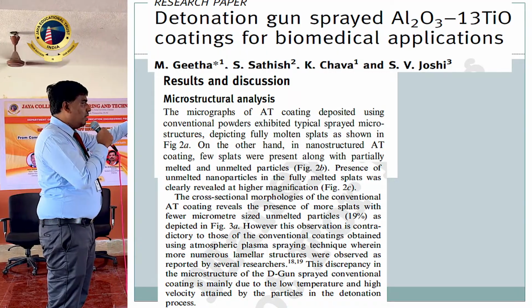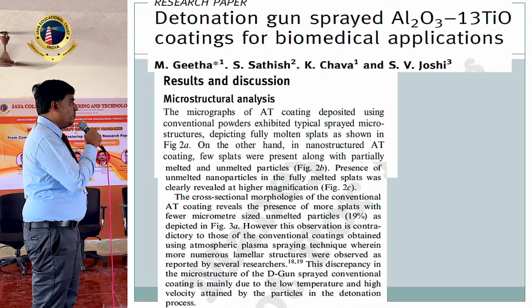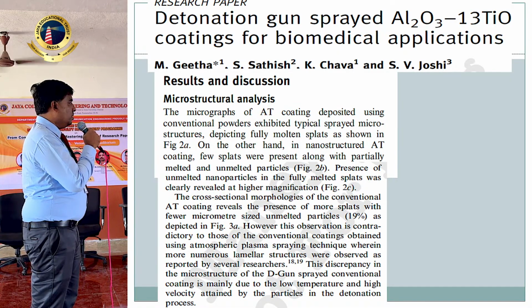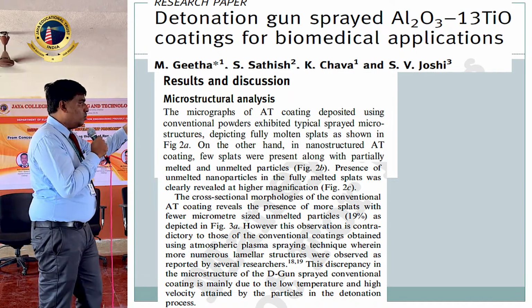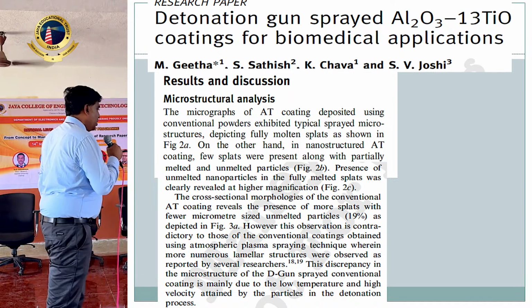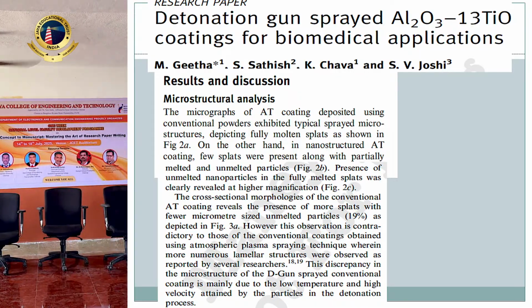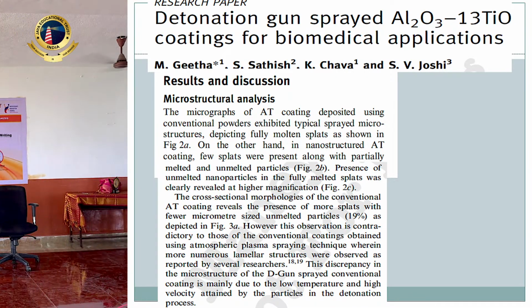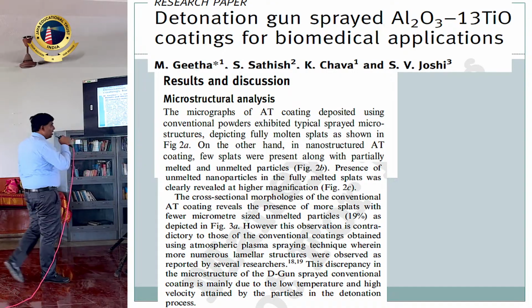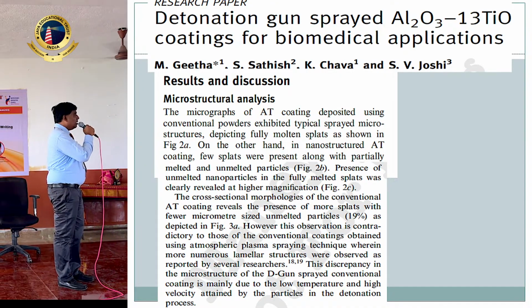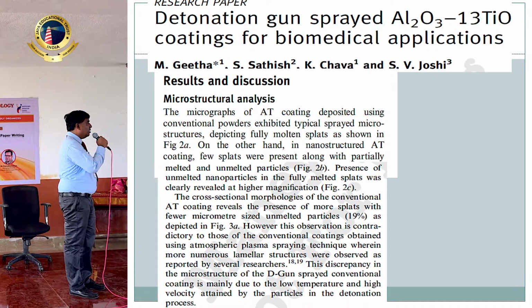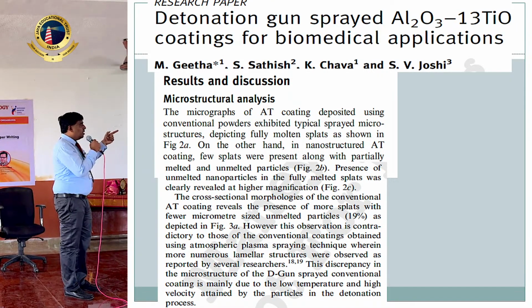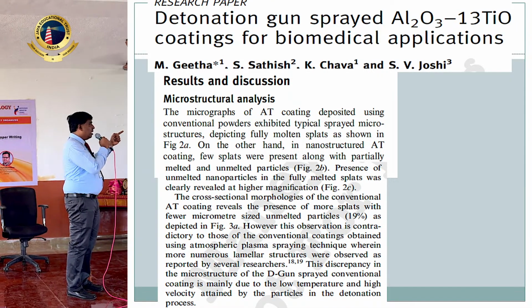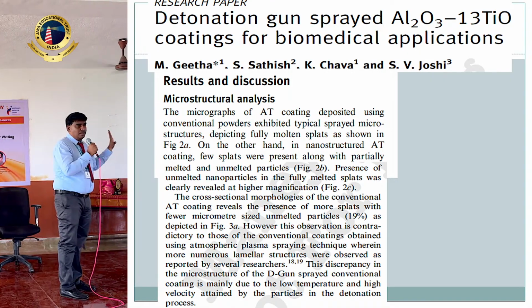And subsequently, I talked about the cross-section. The cross-sectional morphologies of the coating reveal the presence of more splats with fewer micrometer sized unmelted particles (19%), as depicted in figure 3a. After this, I compared my results with the other researchers. Up to this, I got a result. And after this I said that, however, this observation is contradictory to those of the conventional coatings obtained using atmospheric plasma spray technique, wherein more numerous lamellar structures were observed as reported by several researchers.